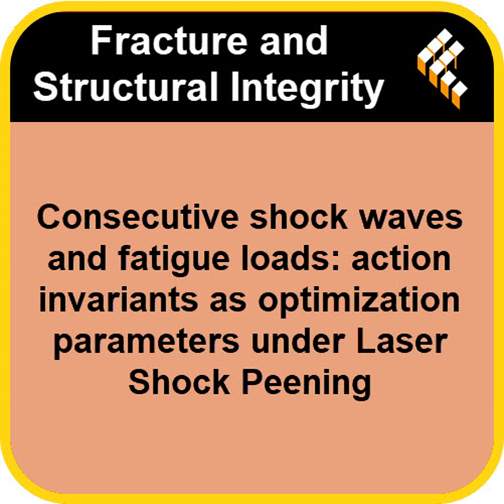1,400 meters a second. That's Mach 4 territory. Yeah. How did they launch it? With a specialized explosive setup, actually. A conical lens arrangement to focus the blast and propel the flyer plate very precisely. So a controlled explosion to simulate the laser shock, but bigger and cleaner. Exactly. Bigger, flatter, and cleaner. And they used sophisticated laser interferometry, VISAR, to measure the shockwave profile very accurately as it entered the target. Crucially, they did this under recovery conditions, meaning they designed the experiment to prevent interfering waves from the sides or back, giving them pure shock data.